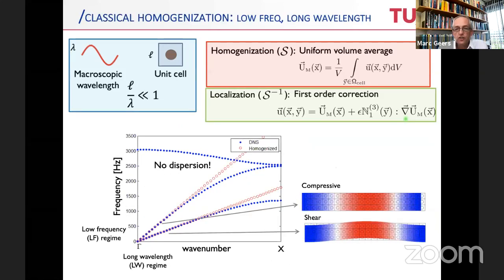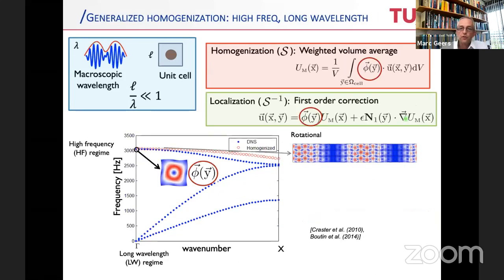Now, in the generalized scheme, we want to go one step further by no longer taking this standard volume average, and that is inspired by the work of John Willis, where we look at projections of the displacement field on particular functions. These projection functions, as we've seen in the problem before, are related to the fact that the dynamics can be characterized by very particular modes. So if you project your displacement field at the microscale on that mode, and that mode is normalized, you recover something like the average amplitude of that mode. That's what this equation expresses.